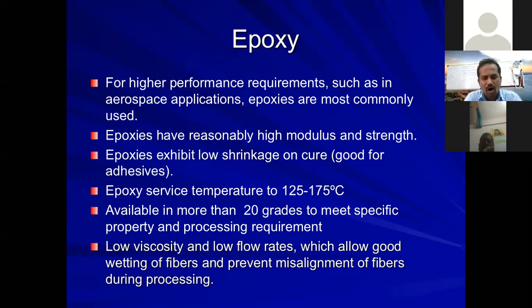One of the most commonly used materials worldwide in the aerospace and automobile industry is epoxy. Epoxy is used for higher performance requirements, such as in aerospace applications. Epoxies have reasonably high modulus and high strength. Epoxies exhibit low shrinkage on cure, low viscosity, and good adhesive properties. Very importantly, its service temperature is up to 175 degrees Celsius. Wherever it is possible to withstand up to 175 degrees Celsius, we can use epoxy resins.